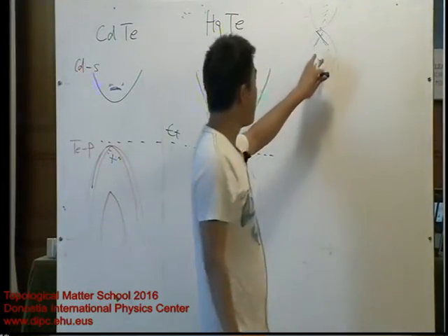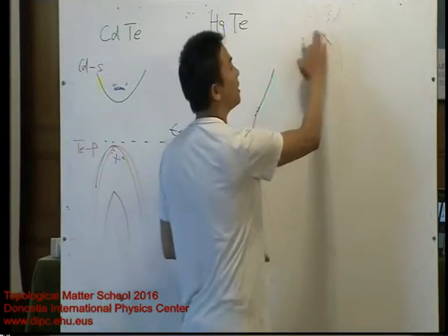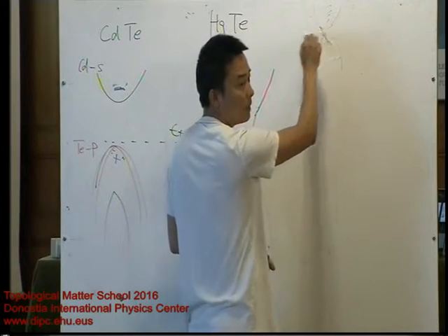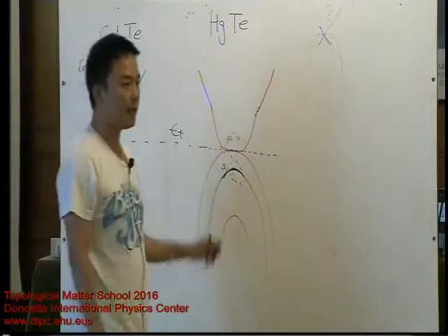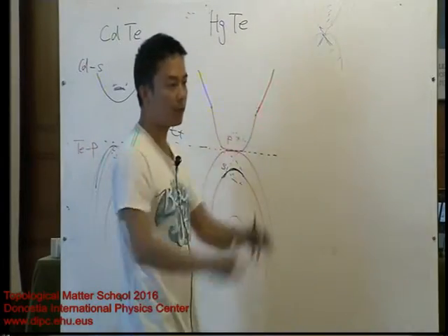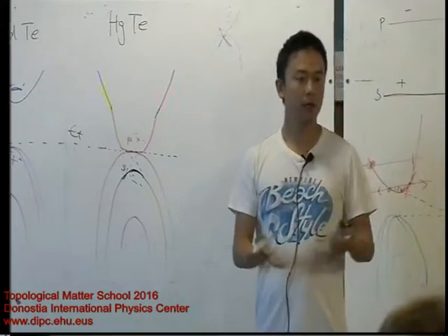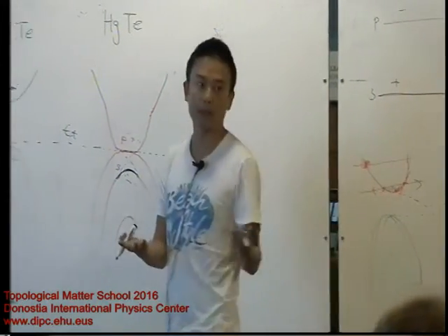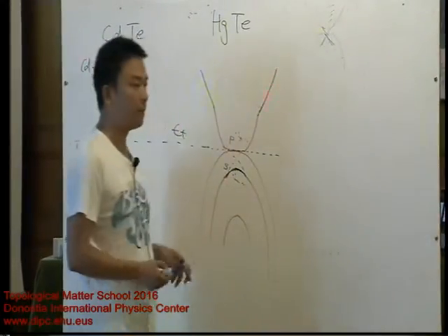And then one practical way, well, it's better if we open this gap, right? Then at least there will be some signal here in the gap. And there are many ways to open this gap. One way, since we argue this degeneracy is related to the cubic symmetry of the 3D material, we just break this symmetry, like apply some strain to make the A, B, C different. At least one of them is different from the others. And when we break the symmetry, we can get a small gap.